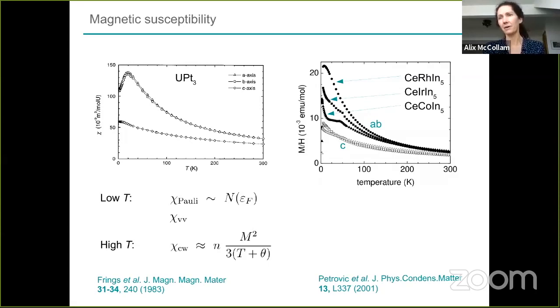So this applies to electron-phonon interactions as well as electron-electron interactions. If there are things that modify the self-energy, then it can modify things like the temperature dependence of the de Haas-van Alphen effect if it's strong. If it's not strong, then you still see the same Lifshitz-Kosevich behavior in the de Haas-van Alphen effect.